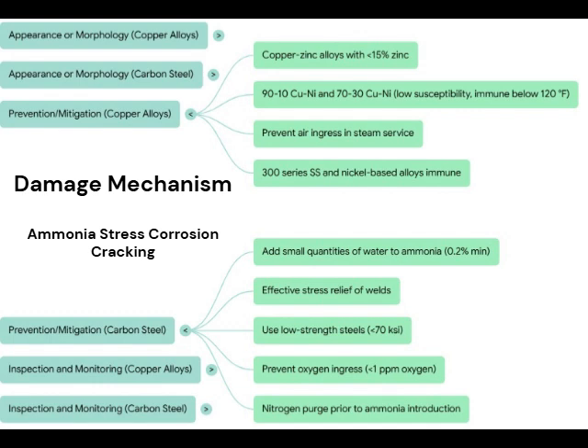Which is oxygen control. You got it. For these big storage systems, oxygen has to be kept extremely low. Like below 1 part per million, 1 ppm. 1 ppm. That's incredibly low. It is. Standard practice is using nitrogen to purge all the air out before you even introduce the ammonia. Because if your oxygen level creeps up, even to say 5 ppm, the risk goes way up, even if you think you have enough water in the liquid. That 1 ppm target is non-negotiable for long-term integrity.